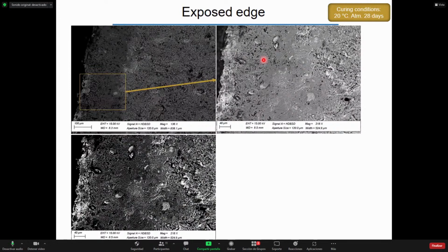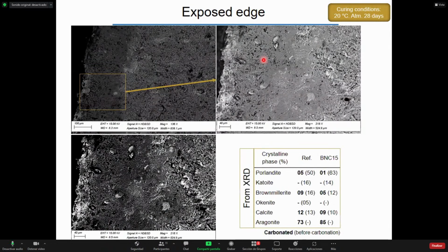To explain this, we examined the exterior part of the cement, and we saw that there is a large area of high porosity. This area shows very low content of portlandite and anhydrous cement, but a large amount of aragonite, which is an unstable polymorph of calcite.